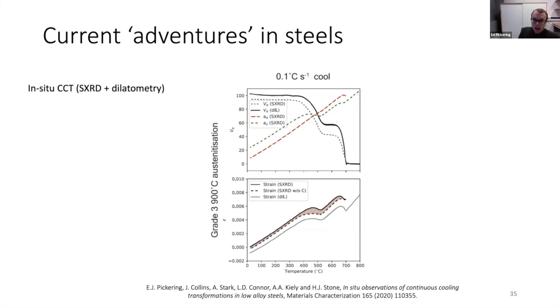And also what we've got is the austenite lattice parameter. The interesting thing, if you pick all this data apart, is that the ferrite fraction you get from the synchrotron doesn't quite match the ferrite fraction you get from the dilatometry, okay? The reason is that when the ferrite forms, it not only causes a dilatation because it's BCC forming in FCC, but it also rejects carbon into the austenite, as we all well know. And this causes the austenite to expand. So you've got to be really careful when you interpret dilatometry data.